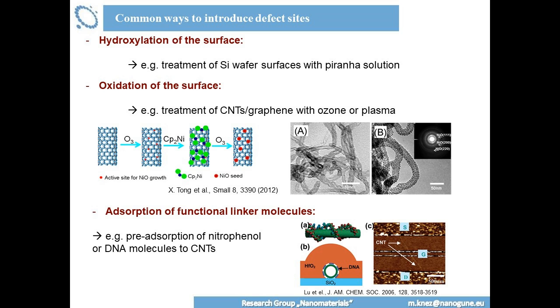Not only the physics, but the chemistry here in this case plays an immensely important role. You have functionalities there, or you don't have them. If you don't have them, you can have a diffusion process happening to the defect site. So you produce a sample, and you may wonder, why the hell do I have a deposition on this spot? There should be none.